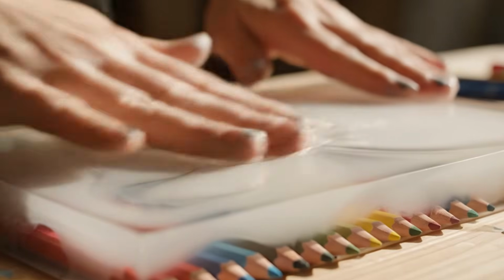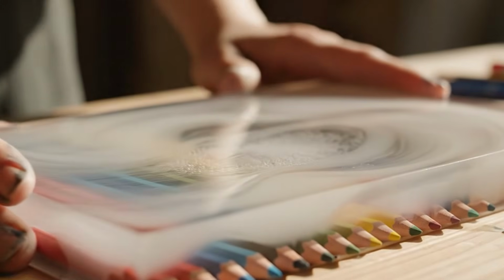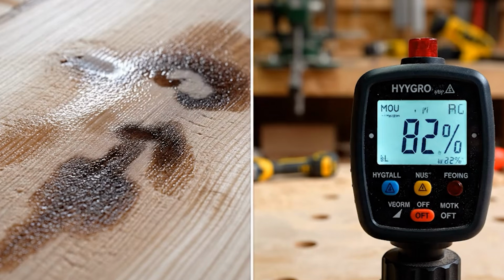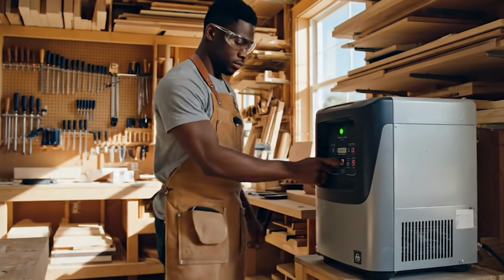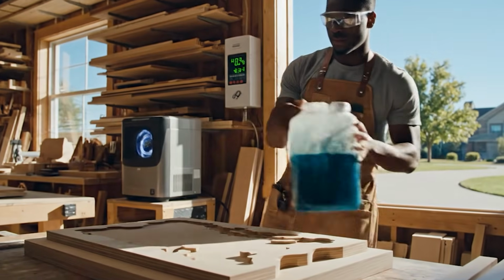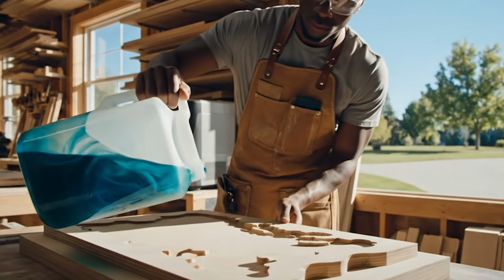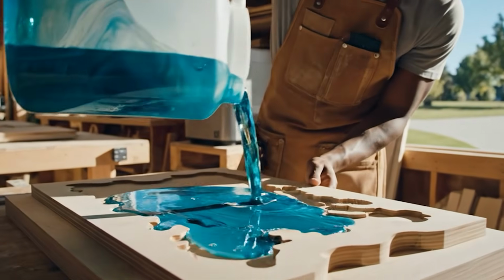Second, the epoxy is cloudy or milky instead of crystal clear. This almost always comes from moisture. Either the wood wasn't dry enough or there was humidity in your shop. Make sure your slab is kiln dried to around 6 to 8% moisture content and try to pour on a low humidity day. If you're in a damp climate, run a dehumidifier in your shop.